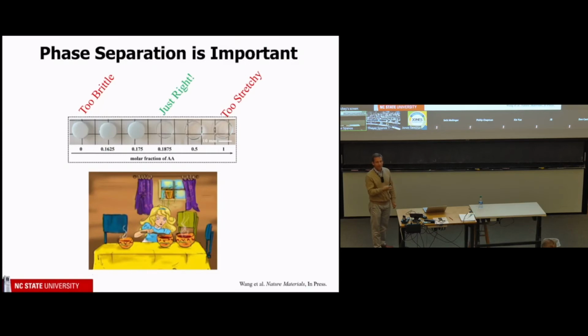The fact that it looks white is a sign that there's phase separation going on, just like how milk looks white. You've got little globules of fat in milk that makes it look white. And here, what happens is the polymer doesn't exactly like the ionic liquid. So as you make it more like this polymer, at some point, those polymer chains, they're like spaghetti noodles swimming around, and they will collapse on themselves and form little domains.